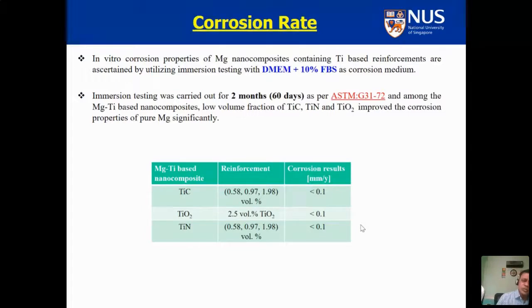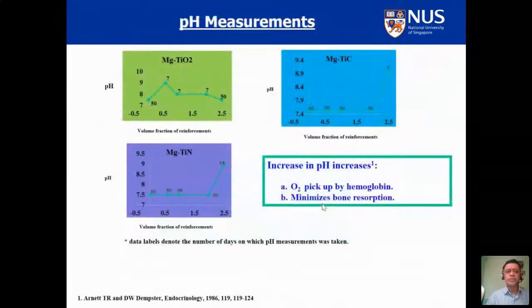Then you have to see how they react in the physiological medium, because at the end of the day, they go in the body. So you have to carry out the corrosion test in the physiological medium using certain international standards like ASTM standard, and we found the corrosion rate is less than 0.1 millimeter per year. So then we talked to the doctor, what is the acceptable rate for you? This is 0.2 millimeter per year. So that means from the physiological perspective, these materials will do a good job.